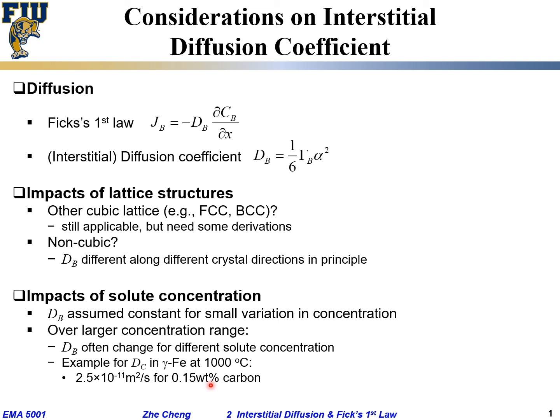On the other hand, they found when the concentration is 10 times higher, from 0.15 weight percent to roughly 1.4 weight percent, the diffusion coefficient actually increased by roughly three times.